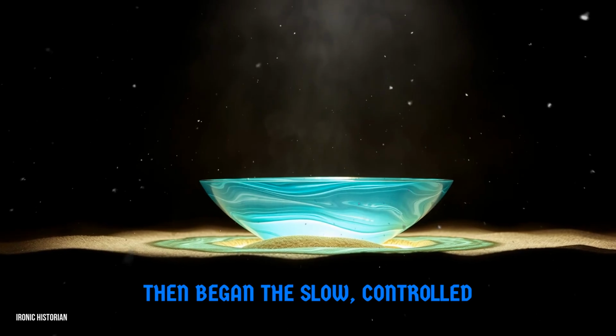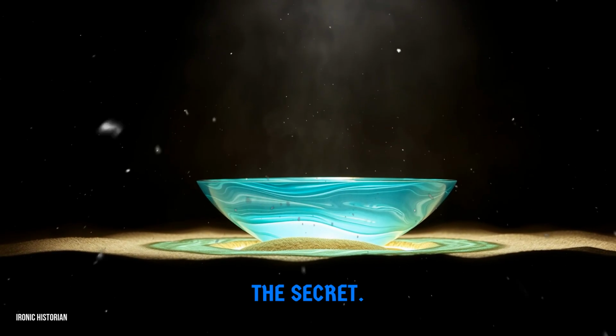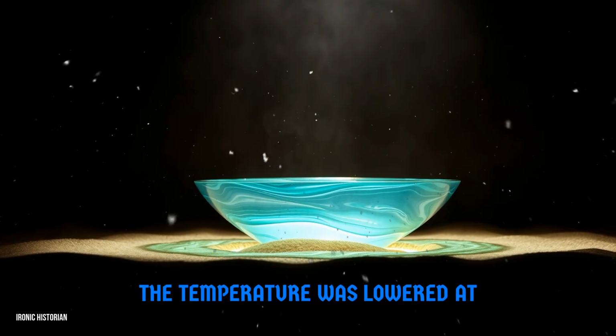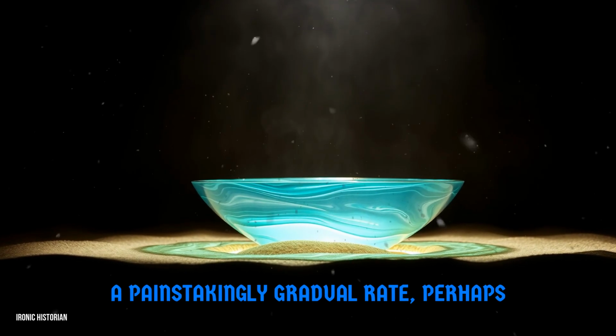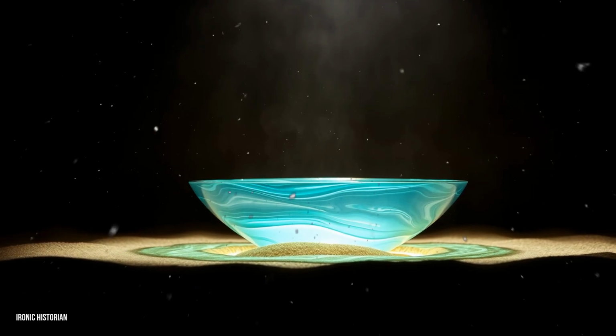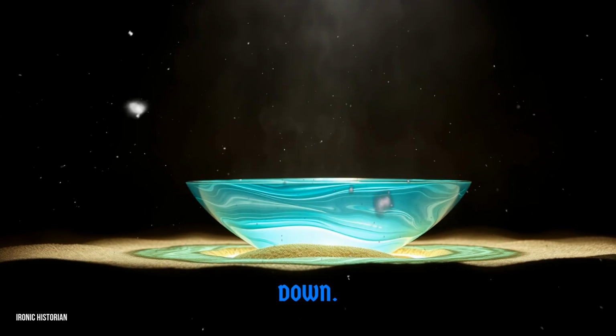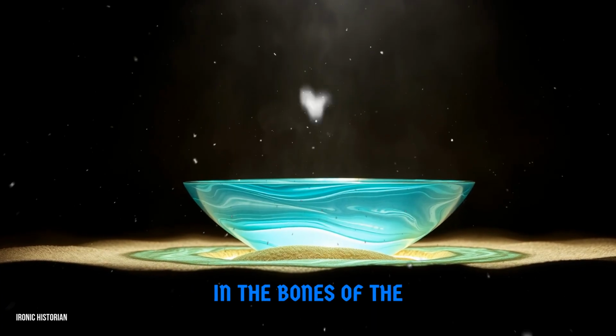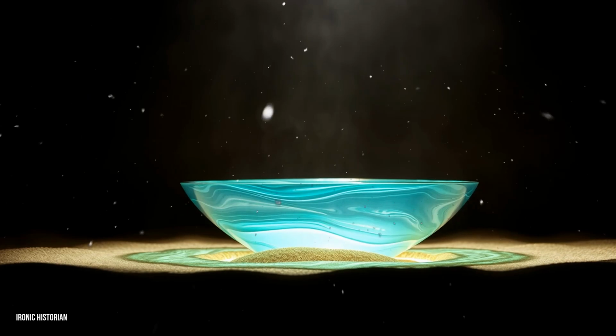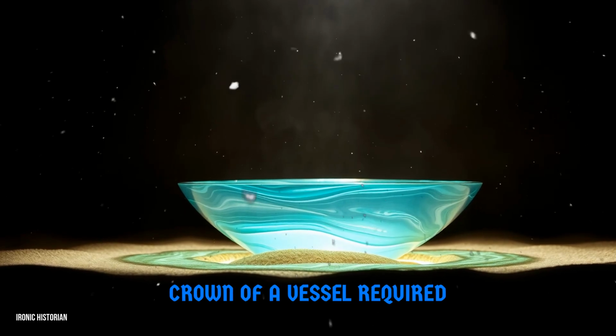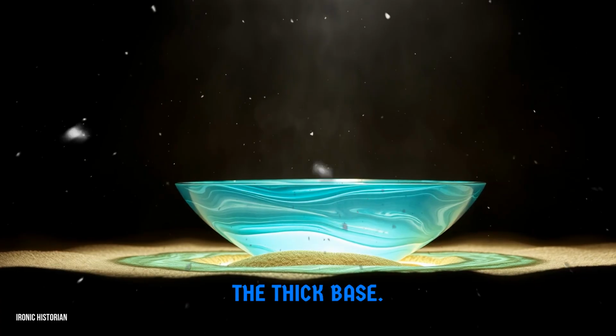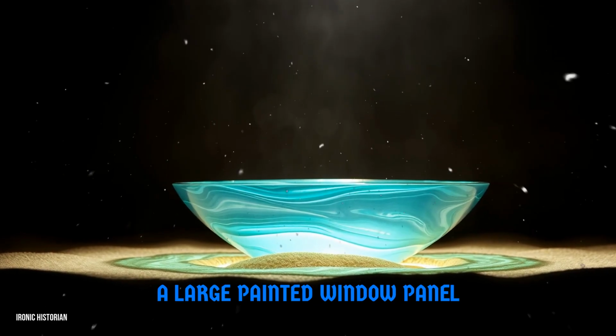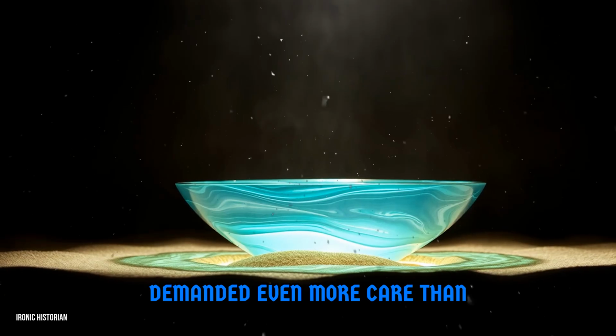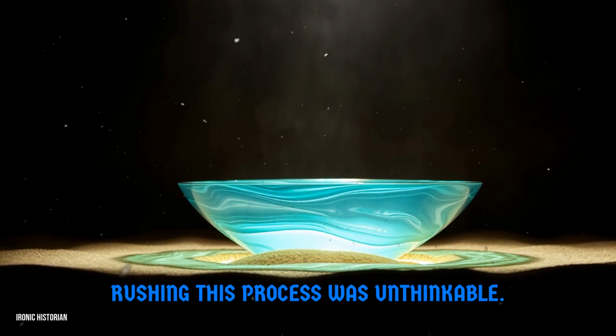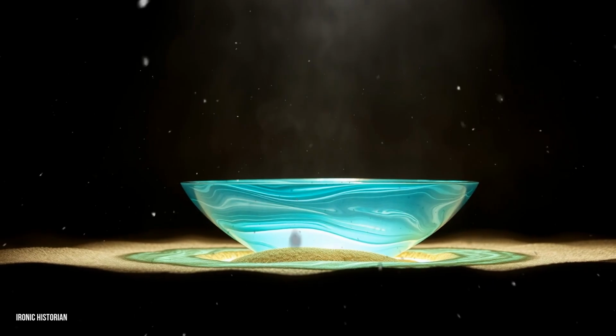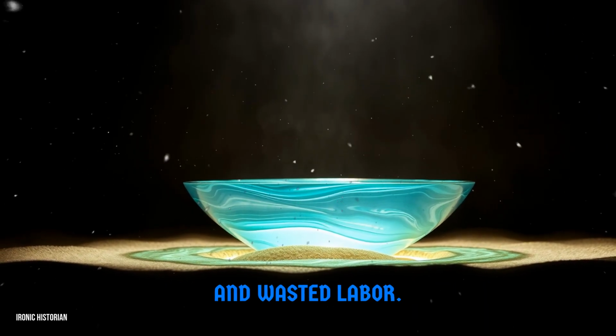Then began the slow, controlled cooling, the true heart of the secret. The temperature was lowered at a painstakingly gradual rate, perhaps only a few degrees per hour. This schedule was not written down. It was a rhythm felt in the bones of the master glassmaker. He knew that cooling the crown of a vessel required a different patience than cooling the thick base. A large, painted window panel demanded even more care than a small bottle. Rushing this process was unthinkable, a guarantee of financial ruin and wasted labor.